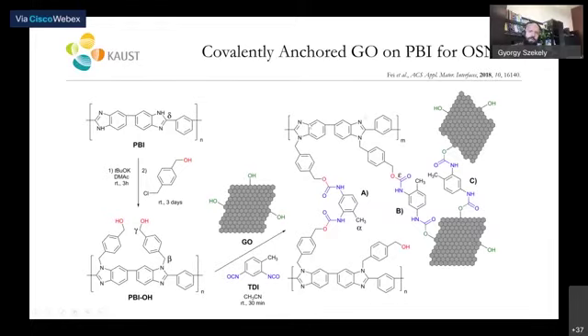So what you can see here is that using this crosslinker, you can cross-link the polymer chains. You can also attach or graft the graphene oxide onto the polymer, and you can also cross-link two graphene oxide sheets. So due to the high cross-linking degree, again, we would expect that these membranes will be highly stable. And in the literature, it was observed before that the addition of GO into membranes usually increases the hydrophilicity and increases the throughput, increases the flux or permeance.